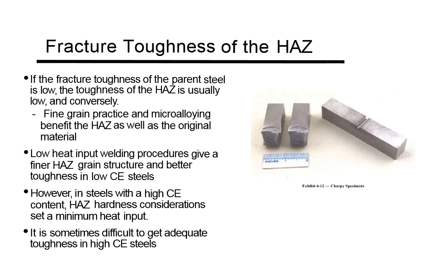That last one is, we used to go round and round trying to qualify weld procedures for use in oil type situations. And they'd want a really high tensile strength and they'd want a really good toughness. And it was really difficult sometimes to hit that sweet spot, because if you get too high of a tensile strength, your toughness is going to go to hell in a handbasket. So it's trying to hit that metallurgical sweet spot, depending on what heat treatment you're doing and what filler materials you're using. It can be a real balancing act trying to get everything just fine tuned. So something to think about when you're welding this, and looking for fracture toughness and a high tensile strength.